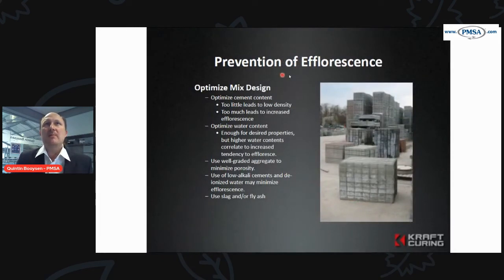How do we prevent this? So, optimizing the mix design. Earlier, we looked at a way of having better graded aggregate. And the better the grading of the aggregate, the less chance of voids forming, the less chance of water floating about inside of the concrete. So let's try to get a higher or a more dense concrete. Too little optimization in your concrete mix design ends up in a lower density of concrete.